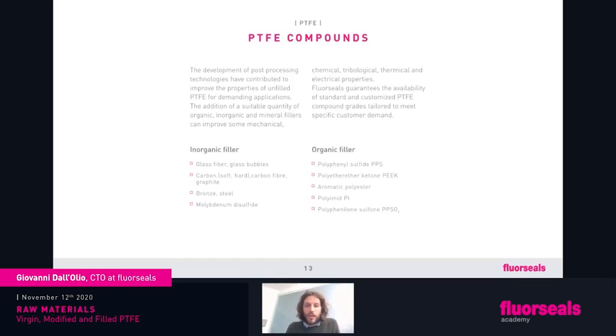The answer is simple, because if we are going to add some nylon to the PTFE, once we get to the sintering temperature, all the nylon will start burning, degrading. And we don't want a PTFE plus something carbon that has a degradation of nylon or whatever we add. So the golden rule is you can select a filler for PTFE that can withstand this sintering temperature. There are other rules like the granulometry, the shape and everything, but I always like to say this because it's easy to remember also. It's nice. So we do have two big families of fillers and compounds, inorganic fillers and organic fillers.